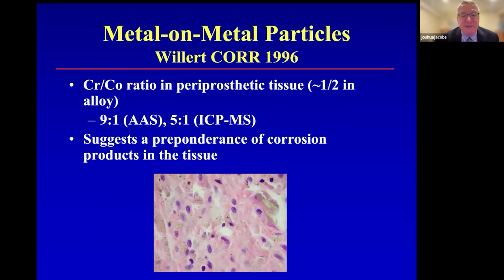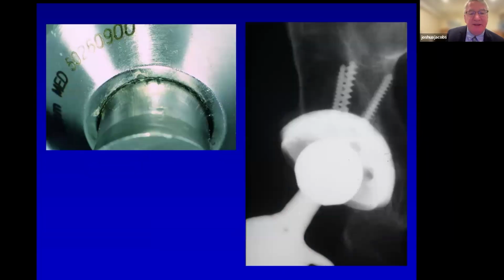Well, if you look at the tissue around failed implants, the chrome to cobalt ratio is reversed. In the alloy, the ratio is about 1 to 2, whereas in the periprosthetic tissue, it's 9 to 1 or 5 to 1, depending on how you're measuring it, either atomic absorption or inductively coupled plasma mass spec. So what's actually in the tissues is not wear debris, it's corrosion debris. So it's either corrosion products from the nano debris that are there or potentially precipitates from the metal ion coming off of the surfaces that complex with salts or local proteins that leads to this corrosion debris.